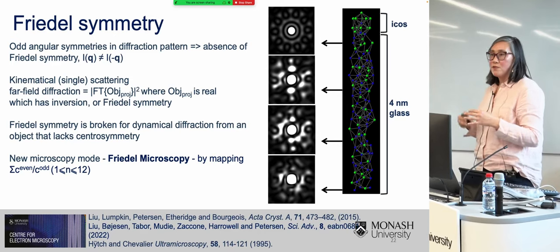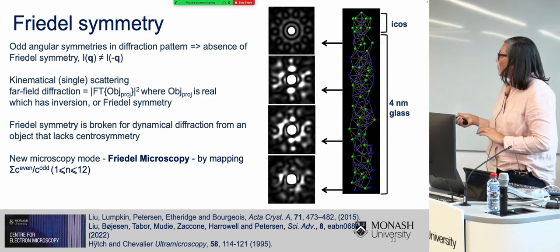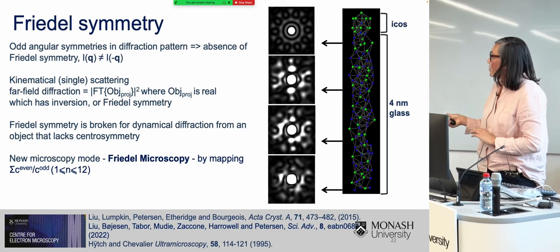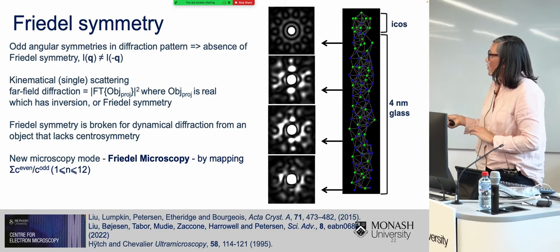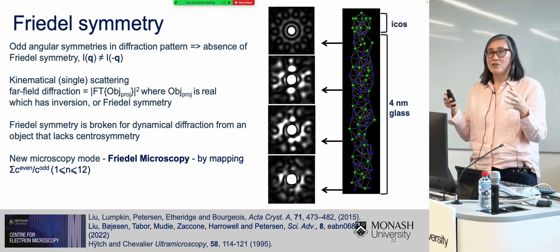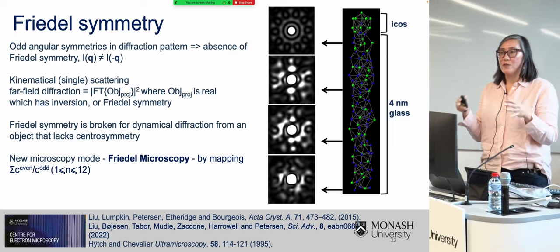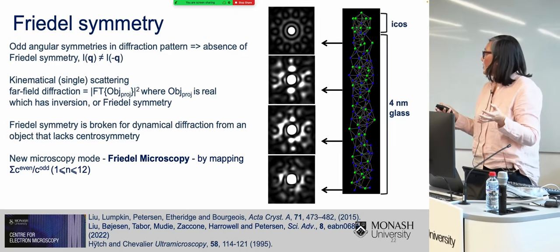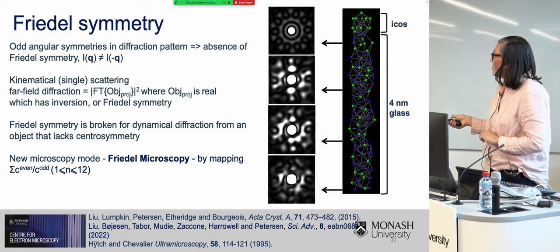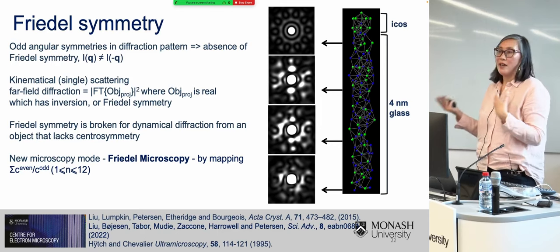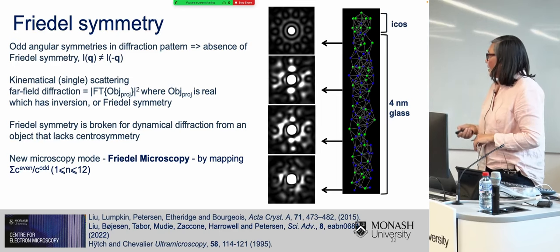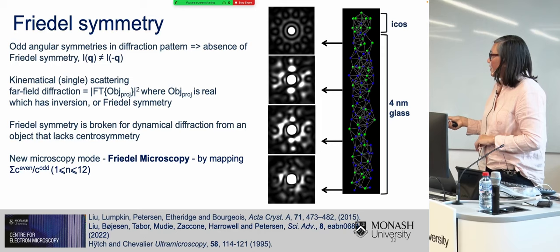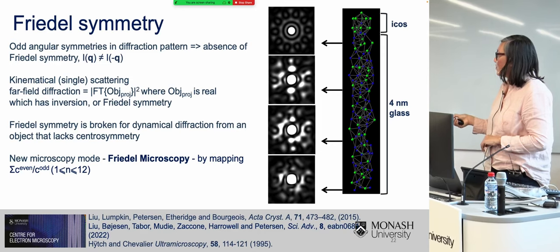Now, we know from scattering theory that if you have kinematical scattering or single scattering, then your far field diffraction pattern is simply the magnitude squared of the Fourier transform of your projected object. And the projected object is in general real, and so that means that under kinematical scattering conditions, you will automatically have inversion or Friedel symmetry. It doesn't really matter what your object is. However, Friedel symmetry is broken if you have dynamical diffraction from an object that lacks centrosymmetry.